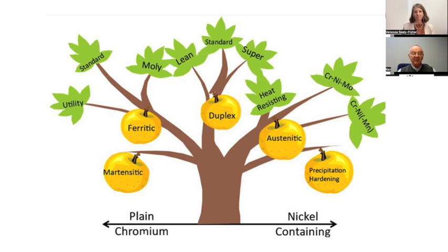If we start off with the plain chromium grades, and we're looking firstly at the lowest branch on the left-hand side, we see that the martensitic grades are where we're going to start. These are hardenable and heat-treatable stainless steels. By heat treatment, we form a martensitic structure, and hence the name. And in order to form that martensitic structure, we need to have a little bit of carbon in the material, but the amount may vary depending on the actual grade.